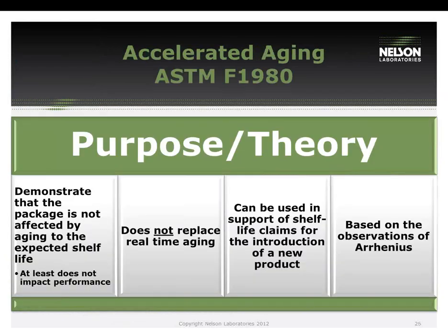The accelerated aging is a way to get your samples to market faster. It's regulated by ASTM F1980, and the theory is to demonstrate that the package is not affected by the aging to the expected shelf life. It does not impact the performance of the package. The key to this test is to understand that it does not replace real-time aging. Real-time aging is the requirement. Accelerated aging is the option. So the test method is based on the observations of the Arrhenius equation.